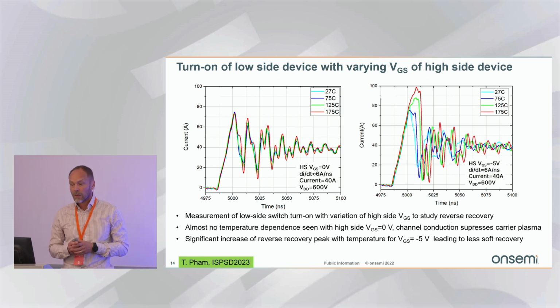And in the graph to the right, you see we have applied VGS minus 5 volt. Then you see that when we go up in temperature, we get a larger peak. That's due to the carrier plasma and reverse recovery, so different from VGS 0, and that can lead to some snappiness also, as you see. So operating with VGS 0 volt is beneficial in terms of reducing the reverse recovery and improving the softness.